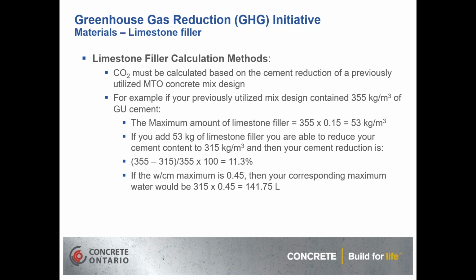And the other thing we have to consider, again, as I mentioned previously, is that it doesn't factor into the water cement ratio. So if your water cement ratio maximum on this mix was 0.45, then your corresponding maximum water content would be 315 kg per meter cubed times 0.45 water to cement, which equals 141.75 liters per meter cubed of water.